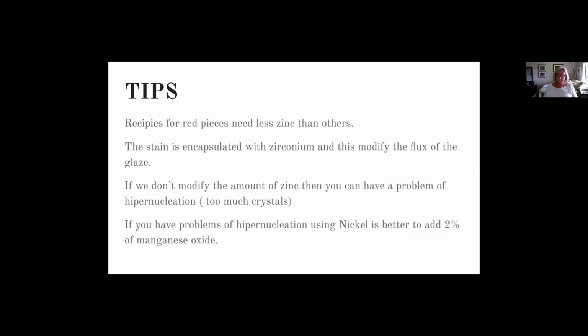Recipes for red pieces need less zinc than others. The stain is encapsulated with zirconium, and this modifies the flux of the glaze. If we don't modify the amount of zinc, then you can have a problem of hypernucleation, too many crystals. If you use nickel and you have problems of hypernucleation, which sometimes happens, you can use a little manganese and that helps a lot.